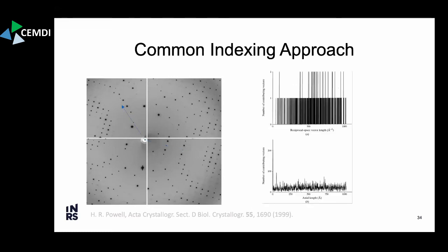analysis. The problem is, if you have a different vector along a different direction, then you don't get a very nice histogram with regular peaks. And when you take the Fourier transform, it looks like noise. This way you can teach a computer how to identify what our eyes can obviously see very easily, that this is a rotated sort of square pattern. But a computer, this is how you can classify that this is one primary axis and this is another primary axis, because you get nice peaks in the Fourier transform along those directions.